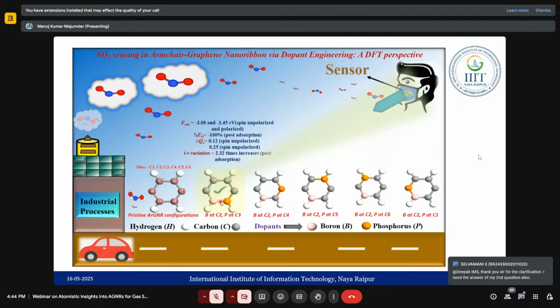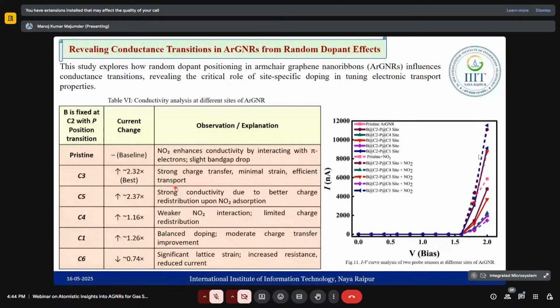And we have seen if we make the boron and phosphorus dopant at these edges, because this is called the armchair edge, correct? This edge, that is C2, C3, or maybe you can say C5, C6. These are the armchair edges, and C1 and C4 are the zigzag edges, correct? So if we make both the dopants in the armchair edges, we can see it will be good for the application. Okay. So here basically these are the results. We can see the boron atom we have fixed at the C2 location, and the phosphorus atom is being shifted to different locations in the case of C3, C5, C4, C1, and C6.